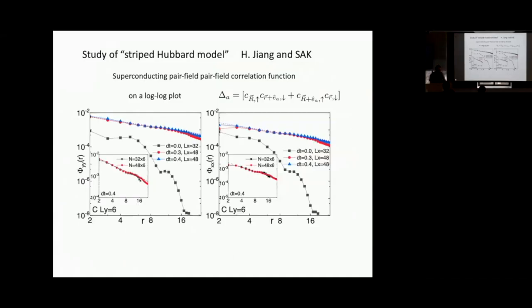Okay, so here's the sorts of results that we get. Here's the pair field correlator. This is for dt equals 0. This is just the nearest neighbor Hubbard model. So again, you can see that the superconducting correlations drop like a stone. And here we have a dt of 0.3. And well, you can see here that the superconducting correlations at, say, 16 lattice sites has been raised by 5 orders of magnitude. It's a really big effect.